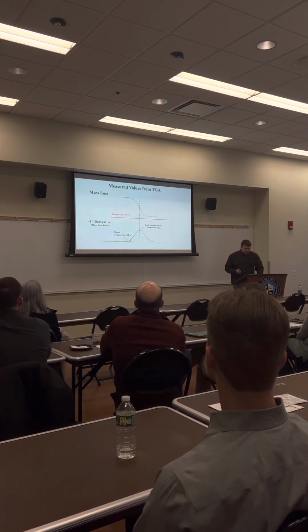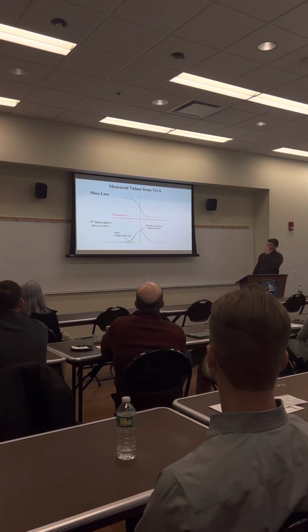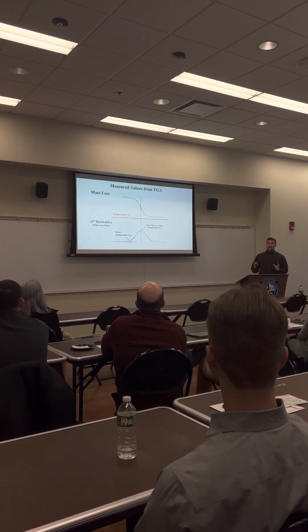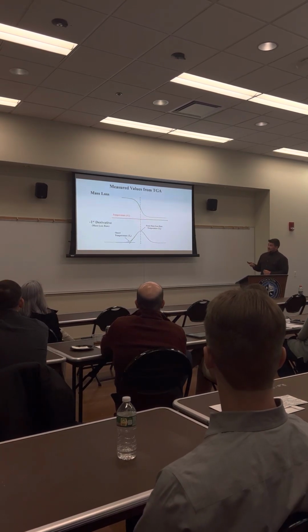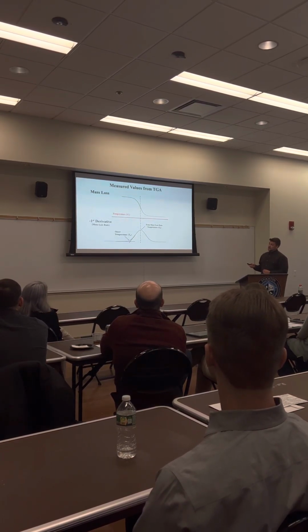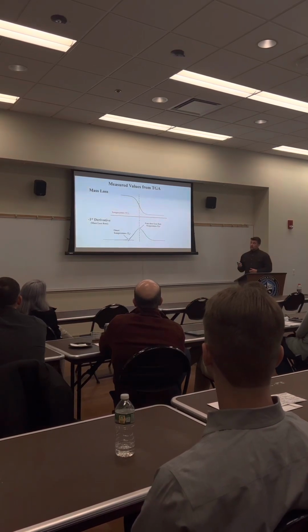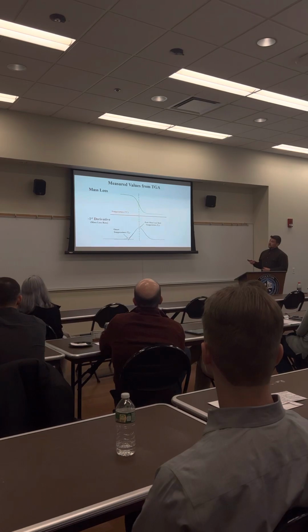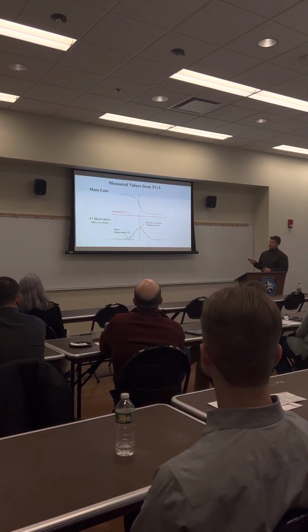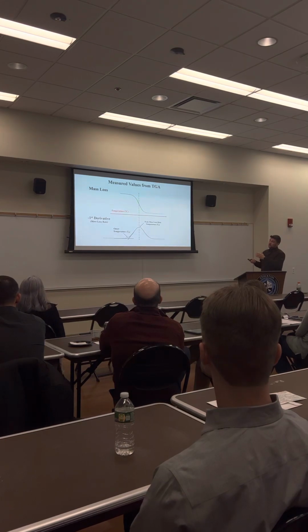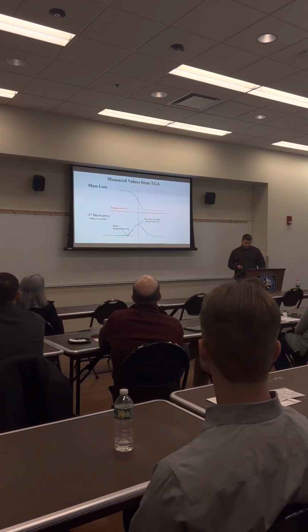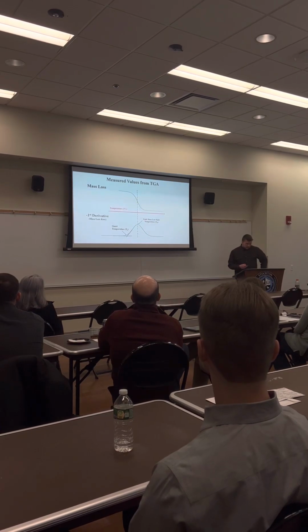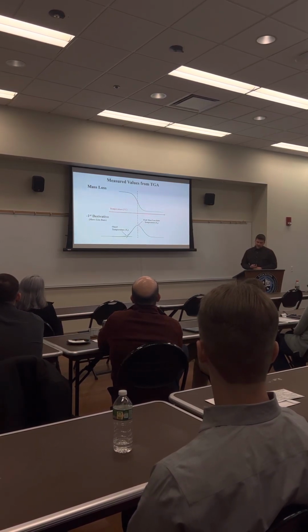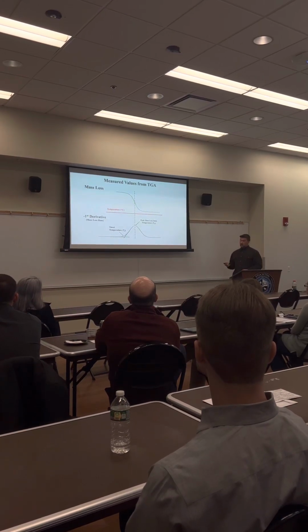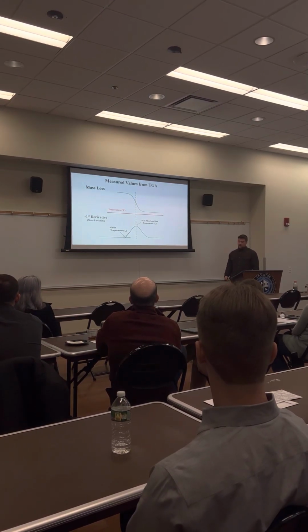So this is the measured value. Basically, this is a breakdown of what we got from the TGA. This is just a mass loss curve, and this is an inverted first derivative curve of that same curve. This dotted line represents the peak temperature as well as the peak temperature on the mass loss scale. We used the STAR-E software and extrapolated the first derivative mass loss curve and inverted it just to show where the temperature value comes from on each plot.